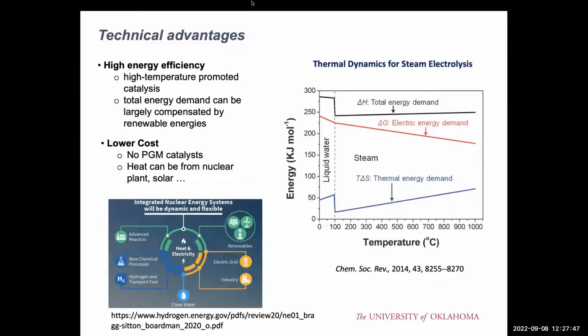such as, for the low temperature electrolysis technology, they need to use platinum to catalyze, to facilitate the water splitting reaction. In this case, we just need to use some very cheap metal oxide material. So the second advantage is the low cost. As I mentioned, we avoid the use of platinum group metal as a catalyst. And we can also integrate the heat from the nuclear plant and also from solar.